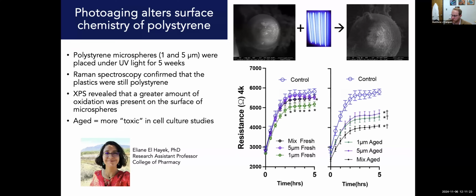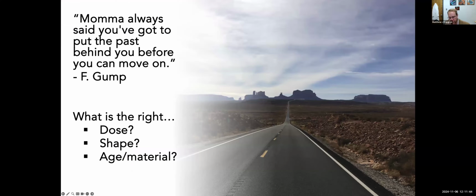And then when we put those into cell culture, and this is just a wound assay where we're looking at the regrowth of cells, the figure on the left-hand side shows the fresh, pristine polymers. We were able to see a minor reduction of regrowth in this assay, but there was a dramatic effect when we aged those particles. So, okay, that completely reset our thinking.